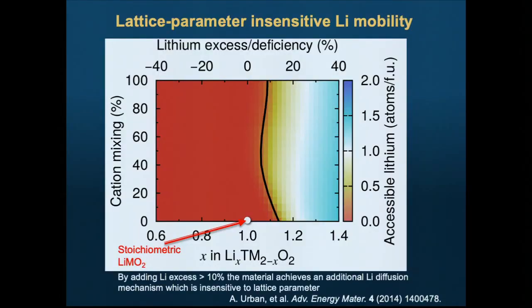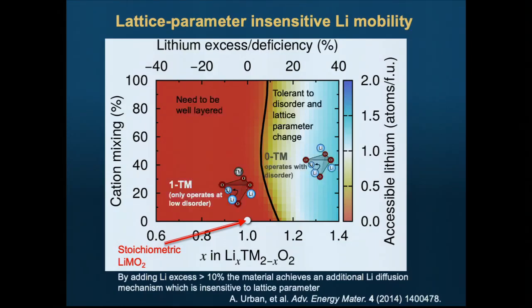This is the design map, essentially. This is the lithium excess. This is the cation mixing, so here you are ordered, here you are disordered. Essentially, when you cross this line, this is the percolation line, you can actually operate with cation disorder, right? And again, you see now why that's important. We can operate with cation disorder, that means we can use any chemistry in the periodic table because we don't care if the ions start to migrate out of their ordered configuration.